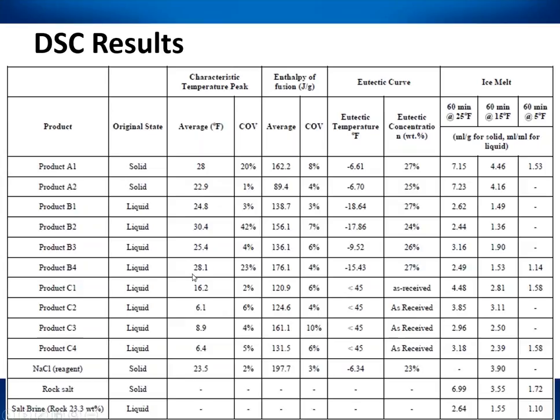And then for the Category B products, these are the agro-based products that are mixed with salt brine. And so your ice formation is starting to occur just kind of below where the complex chloride mineral-based products occurred. And that makes sense because a large component of these products is salt brine. Whereas the Category C products, these are the manufacturer-created products that frequently don't have as much salt brine in them. And you can see that they have a much lower point at which the ice formation will start to occur.